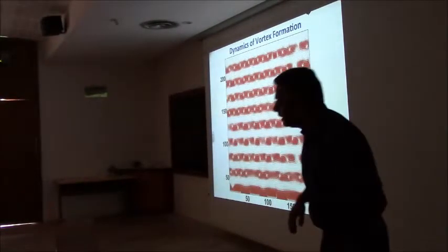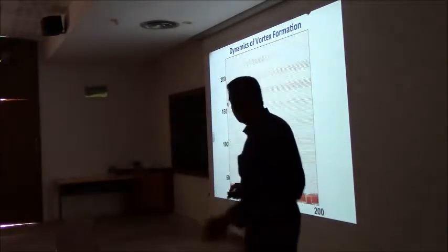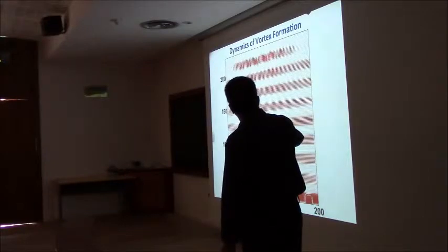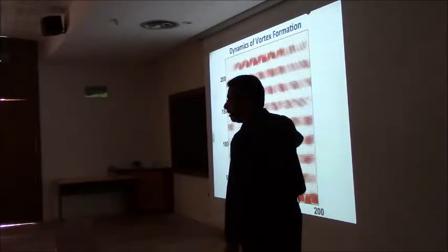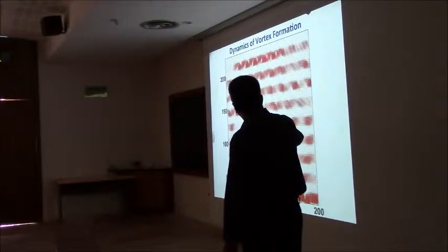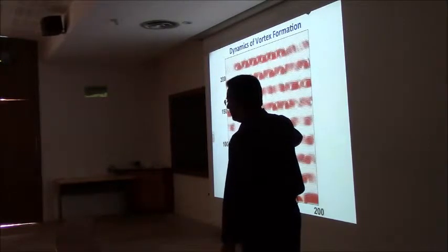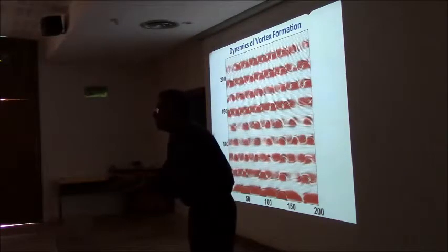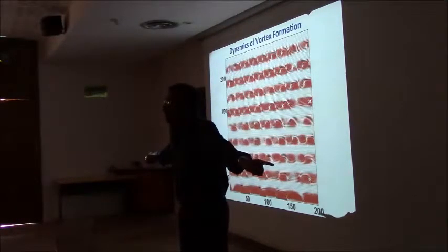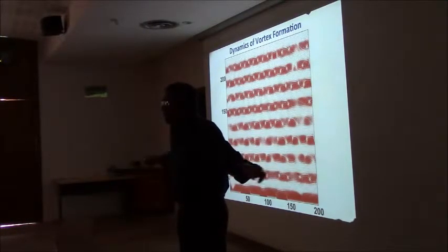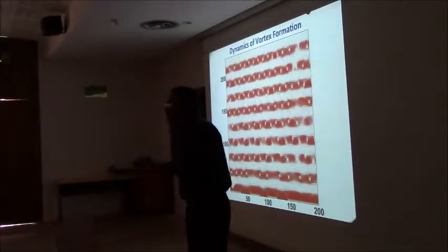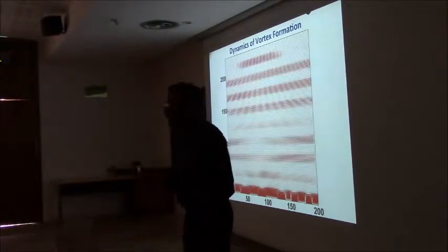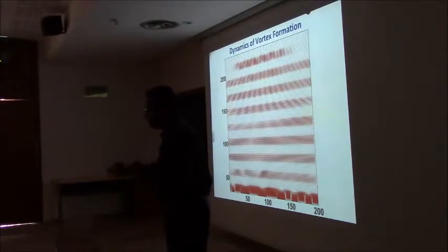So what you'll see in this set of calculations, we haven't done this experiment yet, is the nucleation of the vortex there. But if I put my marker there, that point never moves in the sample. It simply stays there. So one way to think about this is that you have this sheet of lead titanate with the polarization vector in plane. And there's a strain. Therefore, you can accommodate the strain by doing many things. We think it does so by putting in a strain wave. We think it doesn't put in a traveling wave, it puts in a stationary wave.